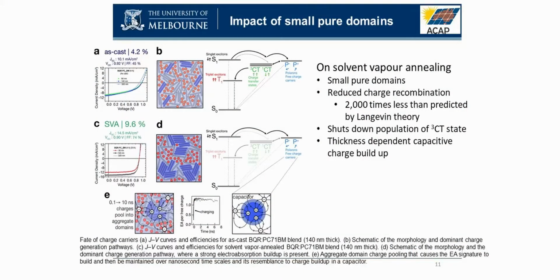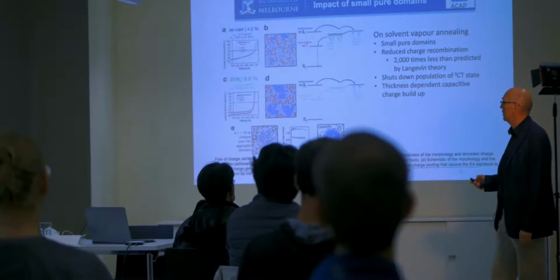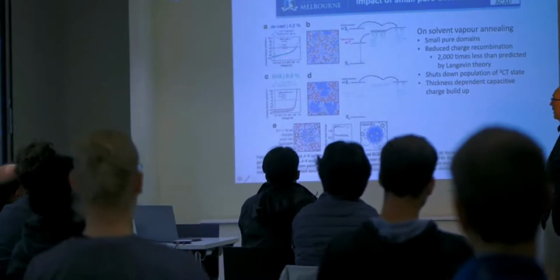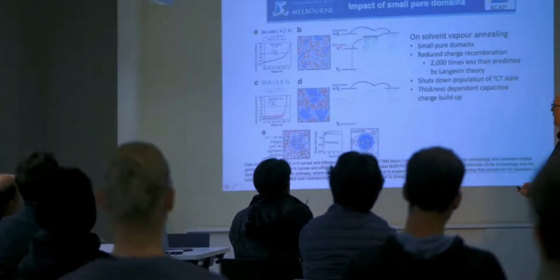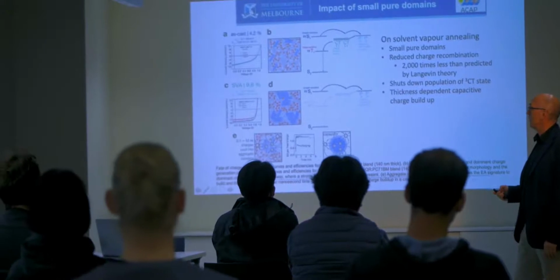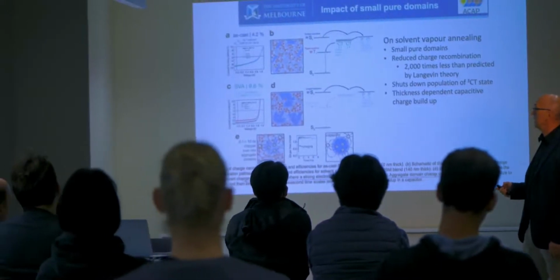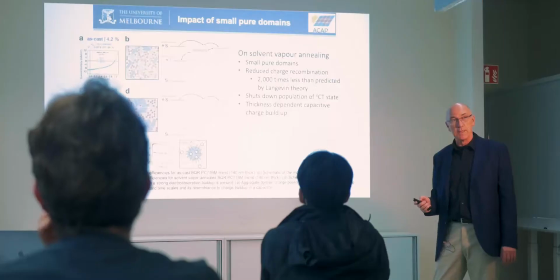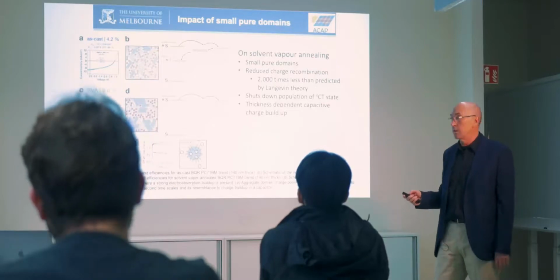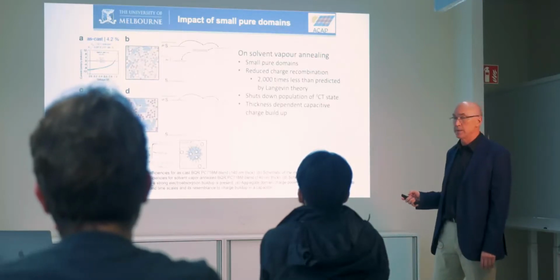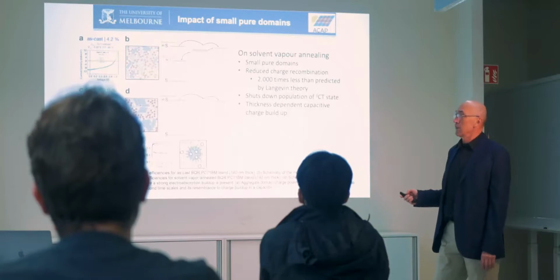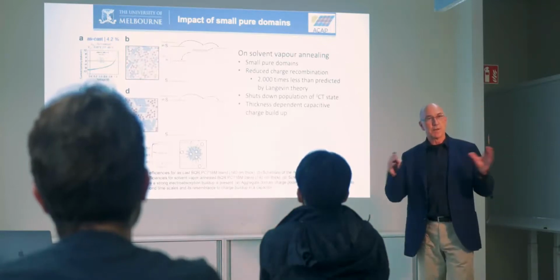And so if we look at that, as cast films, we get pretty poor devices. If you look at these voltage current curves, they're not really good, they're not very square. And so if we look at the model of what's going on in the film, we see that we've got a mixture of the donor and the acceptor, the P and the N-type organic semiconductors all over the place. And then we summarize what's going on in this device. And so there's a lot going on.